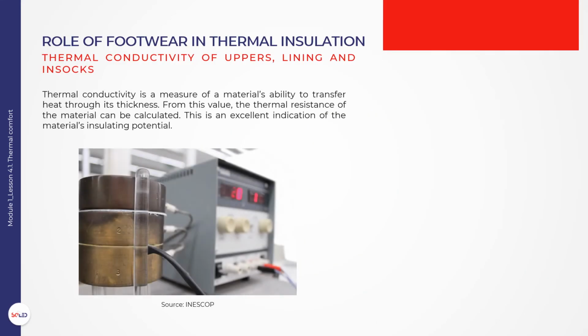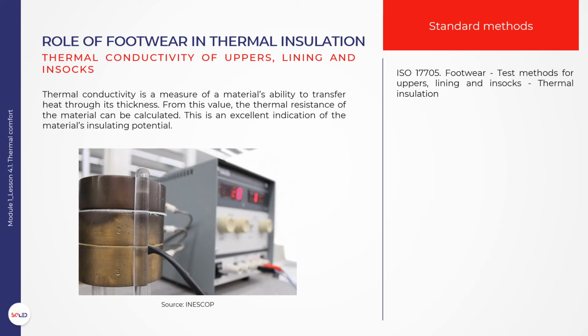Role of footwear in thermal insulation. Thermal conductivity of sheet materials used in footwear is measured by the classic Lee's disk. In this method, a constant heat source is sandwiched between two identical metal cylinders which are mounted with their axes vertical. A test specimen is placed on the top surface of the upper cylinder and a third identical metal cylinder is placed on top of the test specimen so that all cylinders and the test specimen are concentrically aligned. The thermal conductivity of the test specimen is then determined from the steady-state temperature of the three blocks, the exposed surface areas of the blocks and test specimen, and the thickness of the test specimen.